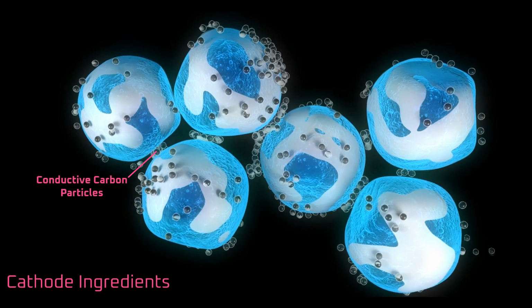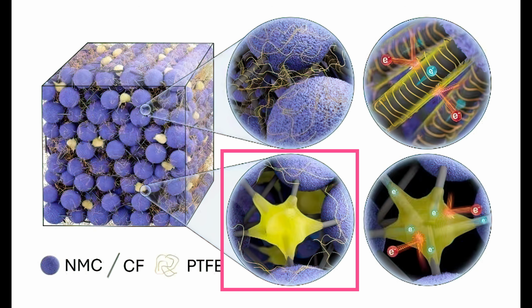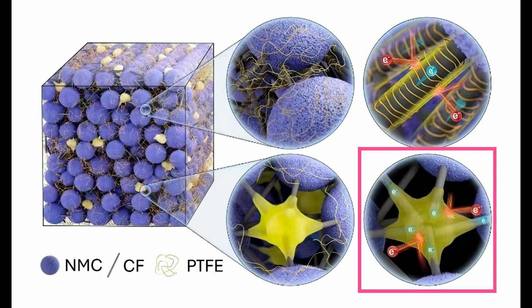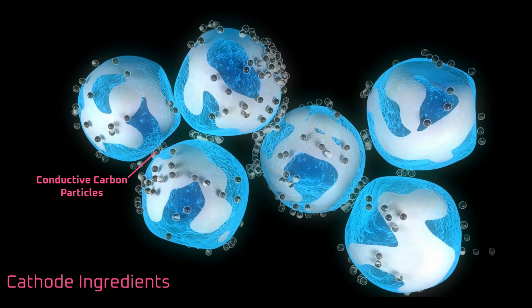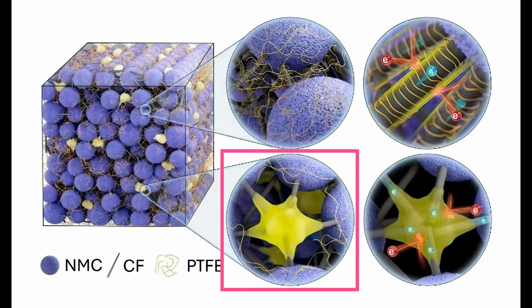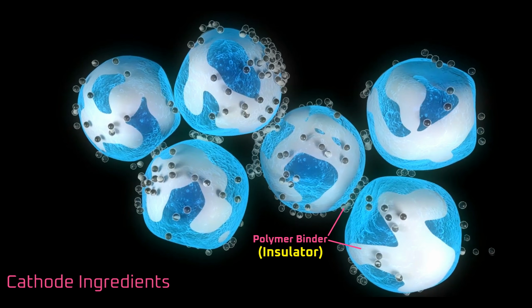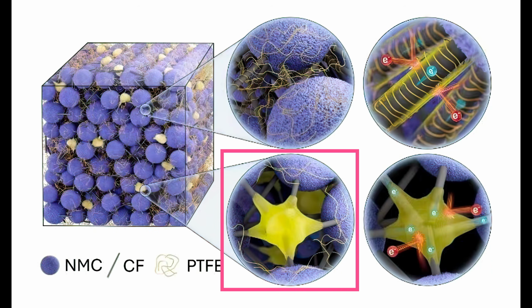The paper proposes replacing the carbon particles in the conductive carbon matrix with a more string-like carbon material, then coating the binder over those strings like electrical sheathing. That would solve three problems at once. First, the binder sheath would insulate the carbon from reacting with the electrolyte. Second, a string-like carbon material would have lower surface area than carbon particles. Third, by applying the binder around the carbon strings rather than between the carbon particles, the binder would no longer create electronic resistance in the conductive carbon matrix.